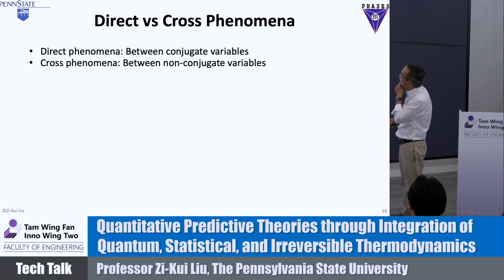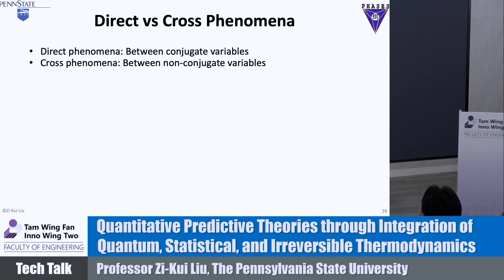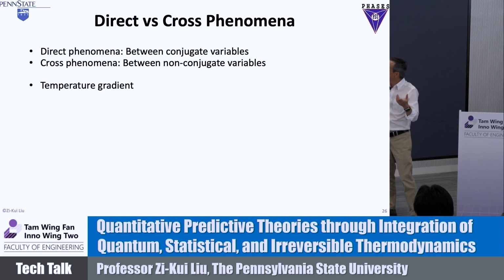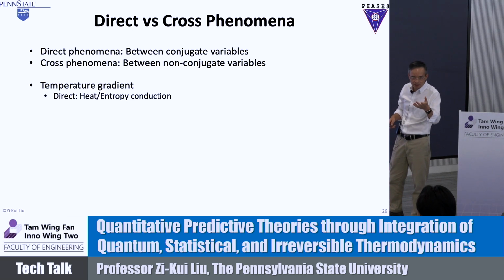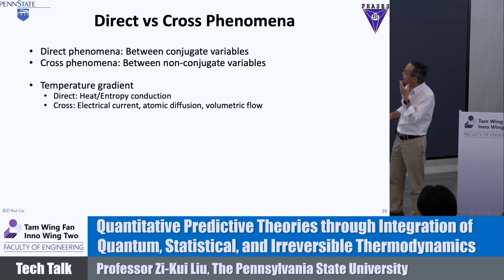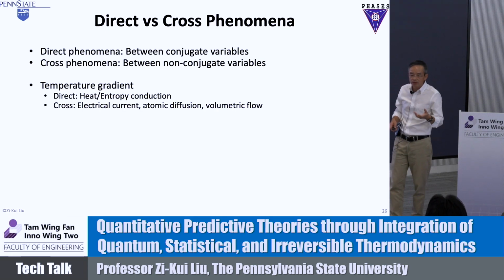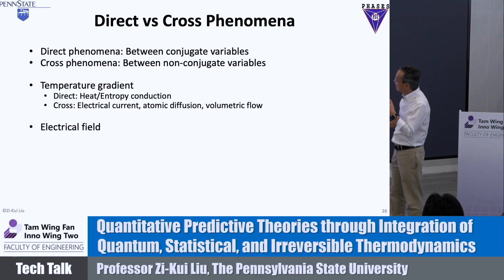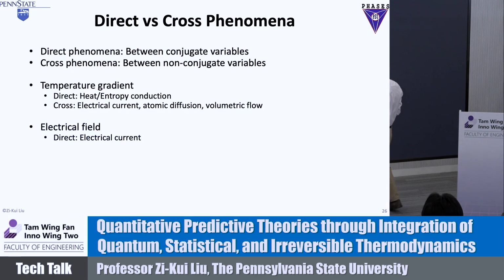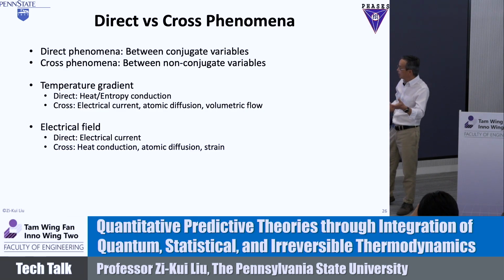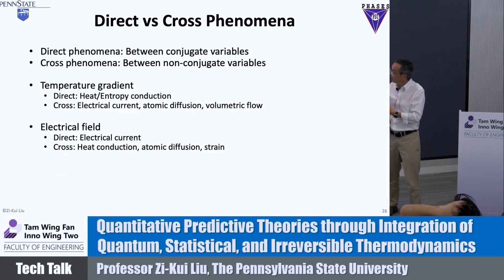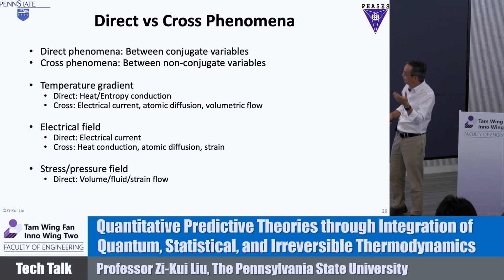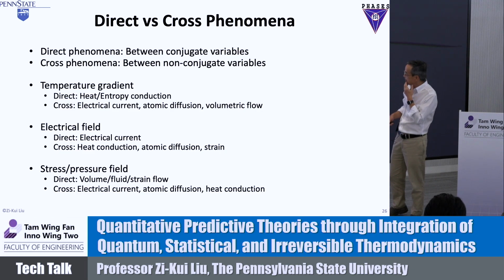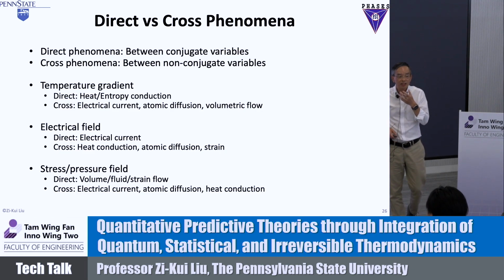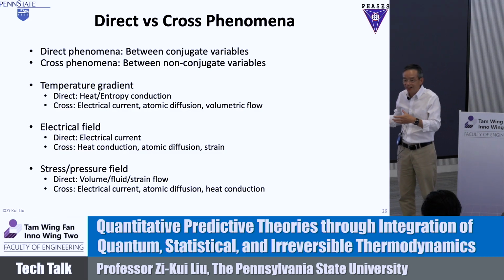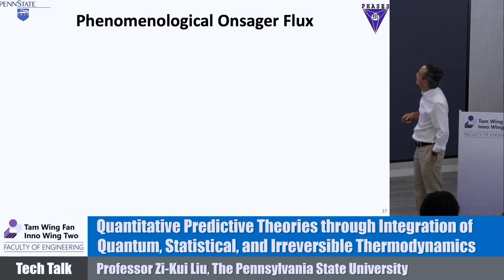So the direct phenomenon is between conjugate variables, and the cross phenomenon is between non-conjugate variables. Now you can say a temperature gradient can generate heat, entropy, which is actually called entropy now. And that's the direct phenomenon. But if temperature drives electron current, diffusion and volume flow, those are all cross phenomena. And then an electric field can generate electricity, that's a direct phenomenon. Then it can also go to heat conduction, atomic diffusion, strain. Same for the stress. Stress, of course, will produce volume change, flow, but it can also generate electricity, atomic diffusion, heat conduction. So it turns out that we have way more cross phenomena than direct phenomena.